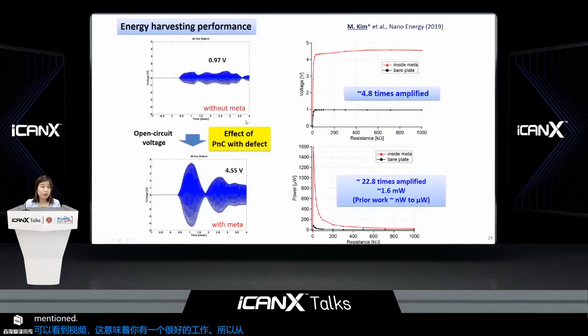So we looked at the energy harvesting performances, and when compared with the energy harvesting devices without phononic crystals, it has an amplified voltage output, about 4.8 times in terms of voltage, and in power even more, more than 22 times. And the most prominent part is that we got about milliwatt level of elastic wave energy harvesting.